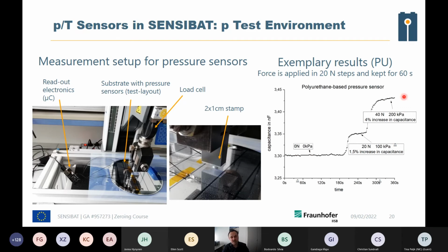We applied in this case a polyurethane material, and then we applied pressures of 100 kilopascal, 200 kilopascal, and you clearly can see that the capacitance of the overall system is reacting on applying this force, and can then be utilized for reading out the forces and the pressure that are active inside this battery cell.